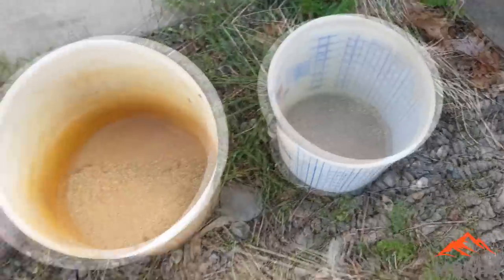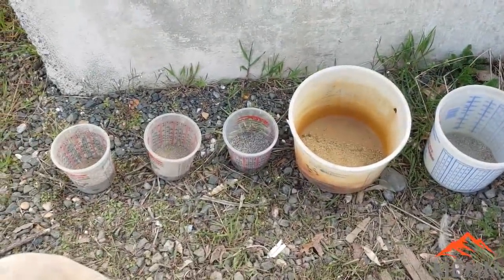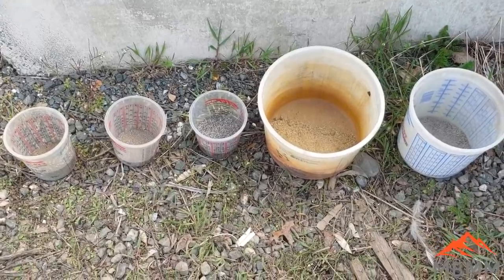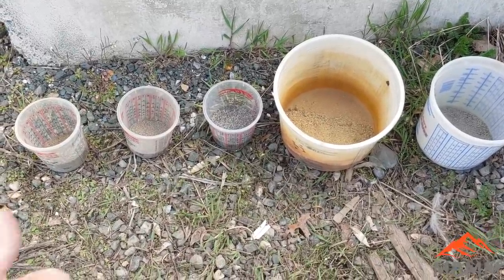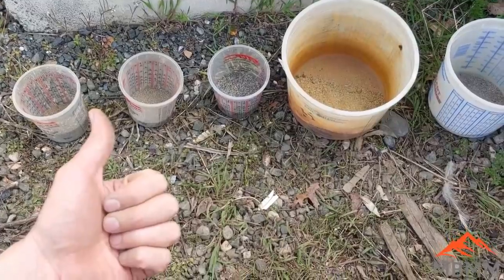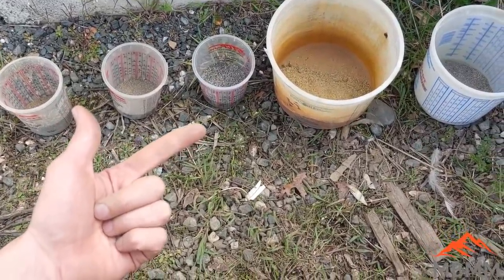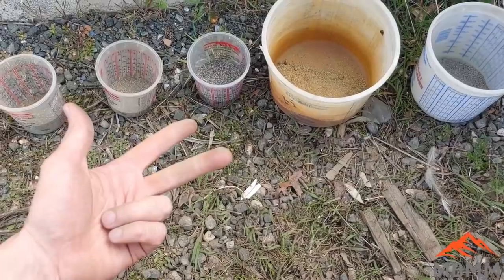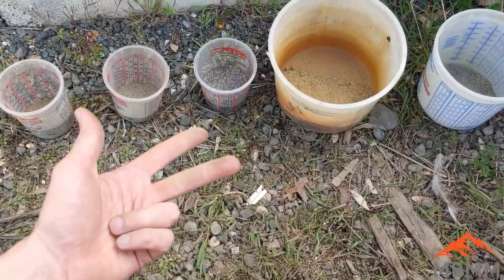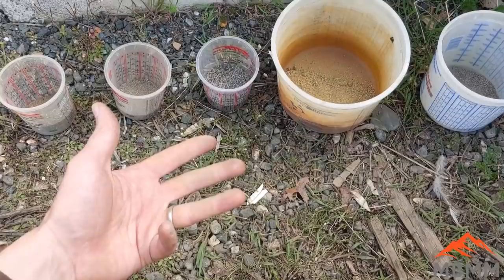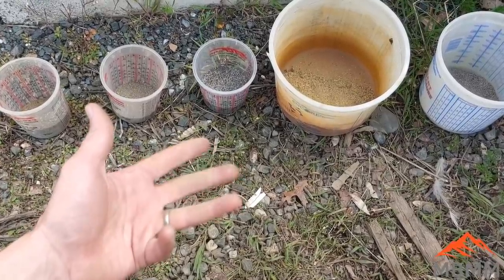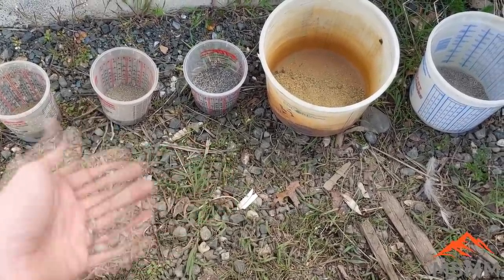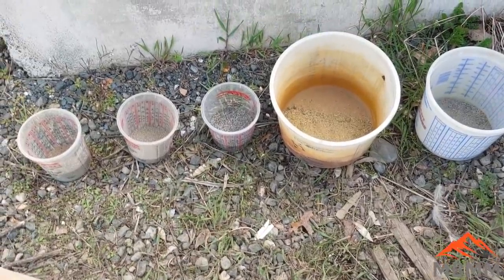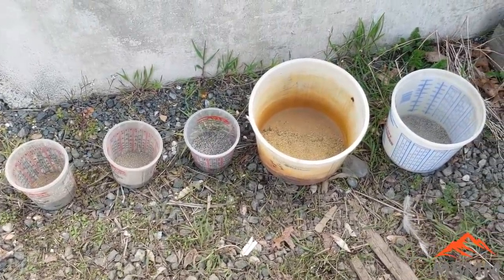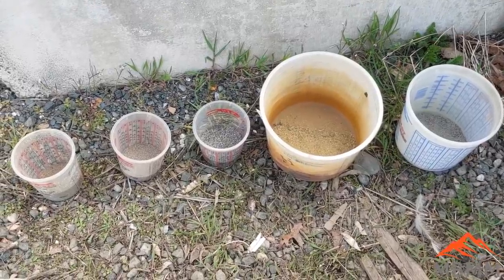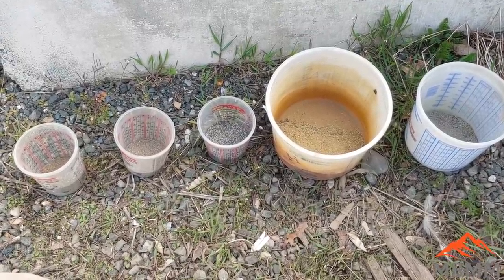And so we're going to run all 5 of these in that order that I went through, and see if we can get a good recovery out of all of these. Our goal, first, is no matte. Second is high percentage of gold recovery. Third is going to be keeping the crucible in good shape. And fourth is going to be a nice quiet smelt that's not boiling, it's not expanding, it's not filling up and flooding the furnace with a bunch of junk and screwing up our furnace lining. So those are kind of our goals for the 5 samples we're going to be running today.